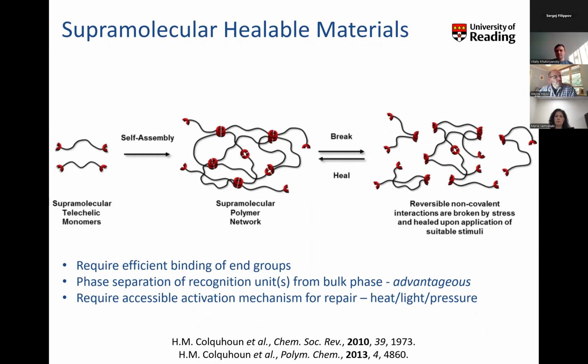So the reversible thermal characteristics led us in 2008 to collaborate with Howard Colquhoun's group and Stuart Rowan's group in America in the area of supramolecular healable materials, where we can use the dynamic association of the hydrogen bonds and the relative weakness in comparison to a covalent bond to have network materials which you can break and anneal in order to heal them. And that's as a consequence of these weak associations of these hydrogen bonding groups.